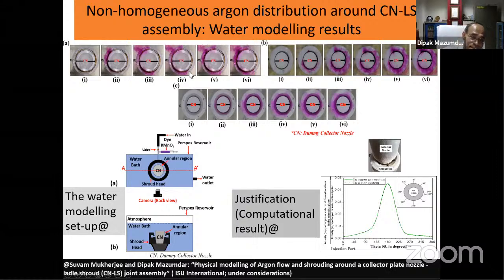But what it shows, most interestingly, is that the argon distribution is not good with a one port system. No matter what the argon delivery systems are, the argon distribution is far from circumferentially homogeneous. This part does not get any argon injection, for example. Here it is somewhat better, and here it is still better, but nonetheless there is no complete uniform encircling of the shroud collector plate nozzle by argon injection. So there is a problem here, and that problem is going to be much more serious when we are talking of this kind of a shroud design.